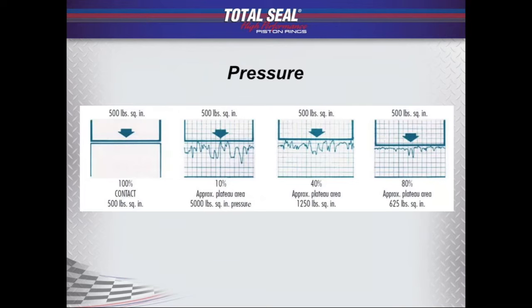This slide talks about pressure, and this is where we're talking about plateau honing. So if you can kind of follow the cursor, no plateau at all. So we're going to say that ring's producing 500 pounds per square inch of force against that cylinder wall. So with no plateau, I've got 100% contact. I've got 500 pounds per square inch of force pushing against the wall. No ability to lubricate, no ability to keep that ring suspended up off the cylinder. It's going to have full contact, and we're going to have a disaster area in a heartbeat, just like a bearing on a crankshaft with no oil. It's not going to last very long.